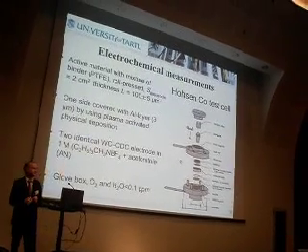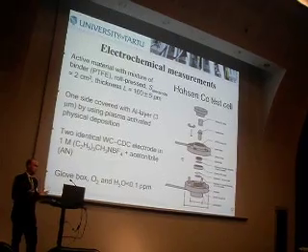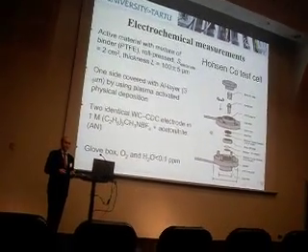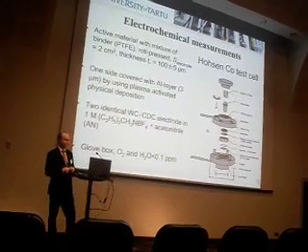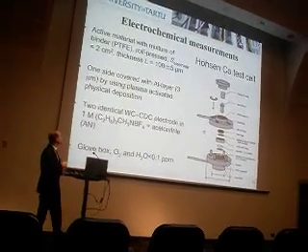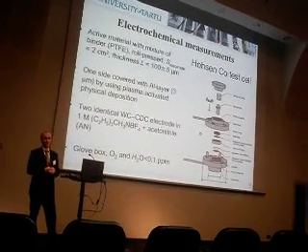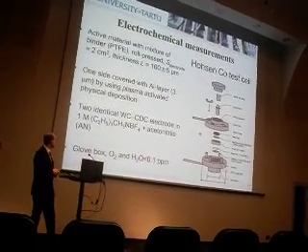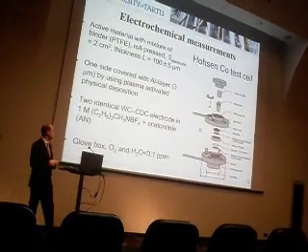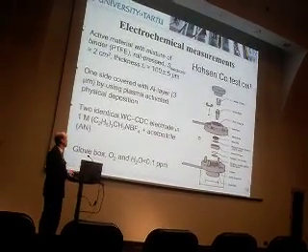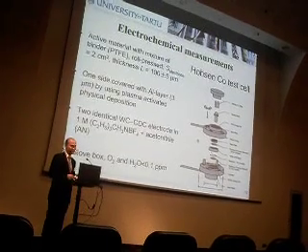Now, we know what the material looks like, but does it work in the way we want it to in an electrochemical cell? For that, we pressed it into electrodes, covered one side of the electrode with aluminium, and then constructed a test cell using this coin-type test cell.